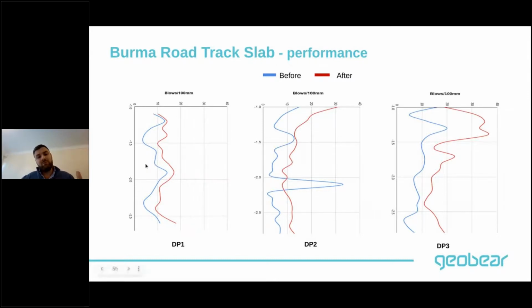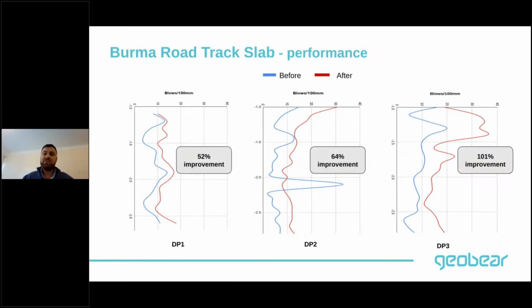And these are 3 different locations where we've done the testing, and you can see there's a significant increase in the blow count before and after the stabilization, and that increase ranged from 50% all the way to 100% increase in the number of blow counts.